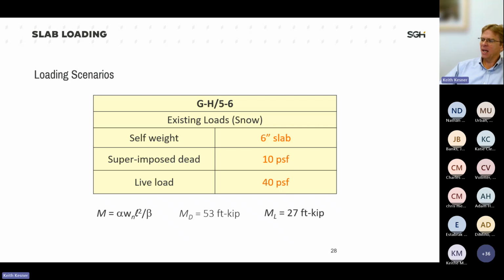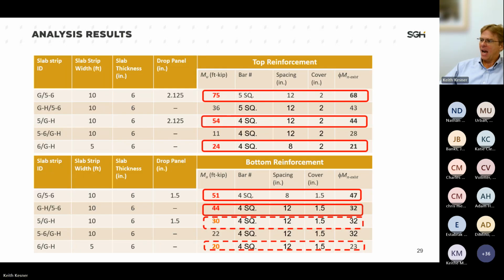So, different loading scenarios that we had for this structure. Live load, superimposed dead. We ended up with different combinations of dead load and live load. And when we started looking at some of the results, we found that the demand, Mu, was greater than the existing capacity based upon where the reinforcing steel was. Not horribly deficient, depending upon the location, 10% deficient, 20% deficient. Not horribly deficient, but still deficient. So a decision was made that some sort of strengthening would be required.